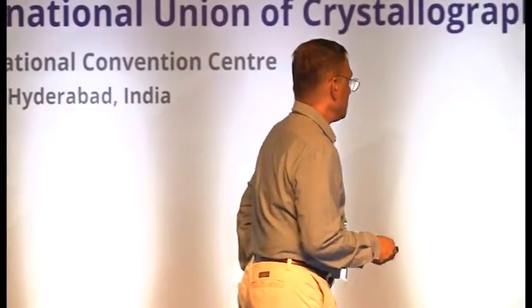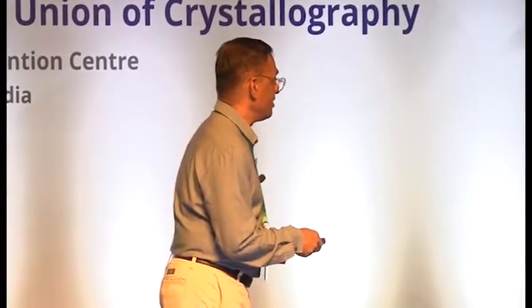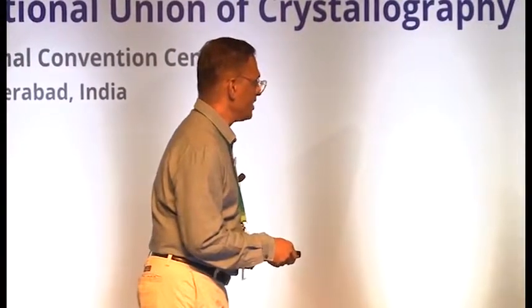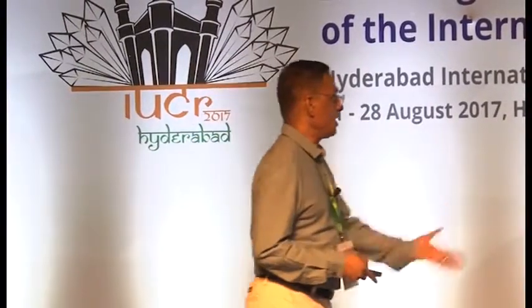When we tried the thermogravimetry of the compound, surprisingly, the lanthanum compound loses diethyl ether at around 82 degrees. That's well above the boiling point of diethyl ether. On the other hand, if you change the metal to praseodymium, it's 69, and when it's samarium, it's about 50 degrees. That is quite interesting, because a simple metal complex is able to retain highly volatile diethyl ether. One would think that probably this diethyl ether is trapped inside the crystal, and that may be the reason why it is not able to come out around its boiling point.